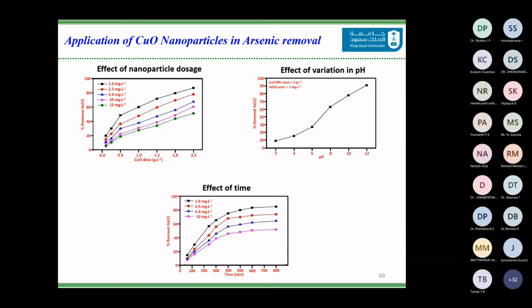However, for this study, we varied the pH as well, between 2 and 12, and we found that at pH 12, these copper oxide nanoparticles have the best removal or absorption capacity at the highest pH. However, when you decrease the pH, the absorption potential also decreases.